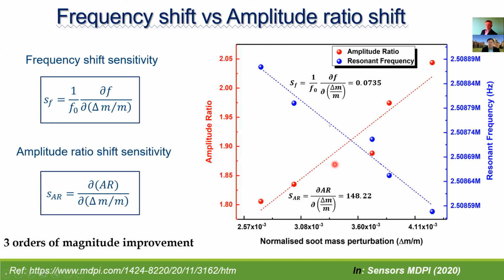If we compare the sensitivity factors based on frequency shift and amplitude ratio shift, it became very clear that the amplitude ratio output metric provided 3 orders of magnitude improvement when compared to the traditional frequency shift output metric. So the sensitivity of this coupled resonator based on the amplitude ratio output metric has been verified for the ultrafine soot particles.